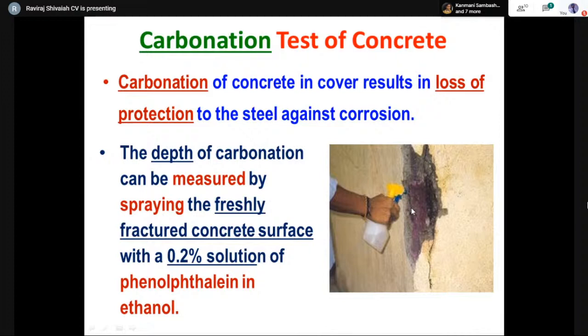So what we do, we break open another 5 millimeters and then redo the test. Again, spray the same 0.2% solution of phenolphthalein in ethanol. If it turns pink, then we need to understand that the carbonation has progressed up to that depth. So having identified the depth of carbonation, you can remove that amount of concrete, and then apply a fresh good layer of cover concrete, and see that you protect the concrete surface so that you can rectify that problem.